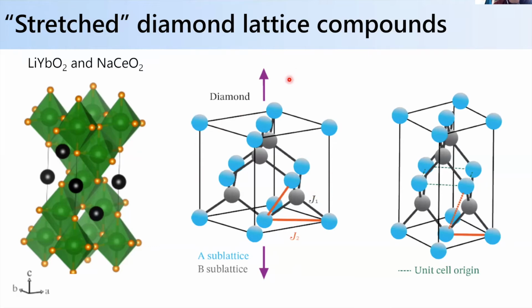And this is sort of a well-known three-dimensionally frustrated material where you can have frustration due to these two equivalent J2 parameters as well as this J1, right? So an antiferromagnetic J2 will drive the system to be frustrated. And so we can imagine just taking this perfect diamond unit cell and stretching it and making it a tetragonal cell. And if you stretch it far enough, then this J2 here moves up, and eventually it becomes far enough that you can just ignore it. Okay, it becomes very weak. And then you can just think of the remaining J1 and J2 terms.